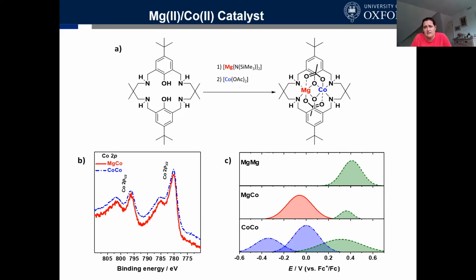Here is some characterization data on this catalyst because it's not so straightforward as the magnesium zinc compound to characterize, because cobalt(II), as you all know, is a d7 electron configuration, and so is paramagnetic. Because of this, we've made use of two perhaps more unusual techniques, one of which is XPS. We did these studies with an academic at UCL, Anna Regoutz. Her work was very useful to help us establish that we hadn't had any oxidation of the cobalt. You can see that the cobalt binding energies are very consistent with cobalt(II), both for this heterodinuclear catalyst and for the homodinuclear analog that we always make so that we can really understand activity increments.